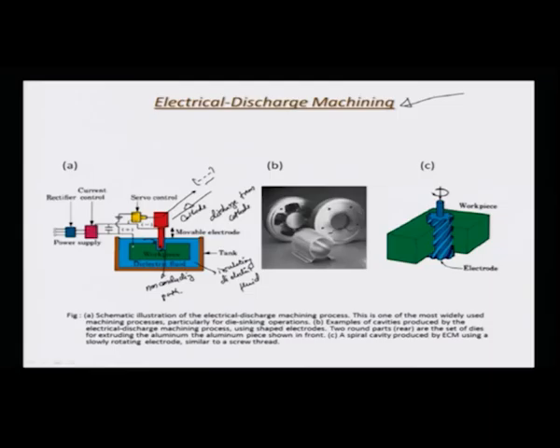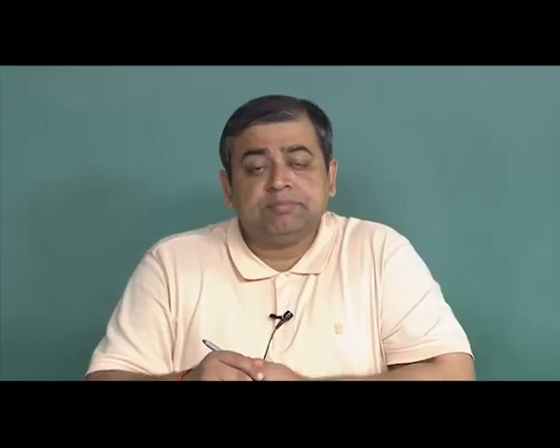So, a discharge is typically a momentary stream of electrons which is released by the cathode, and they are driven by the field and the positive potential of the anode, and they are accelerated, and then in this condition they hit upon the workpiece, which leads to a situation where this discharge creates an ablation or a thermally ablated zone with a melt pool.